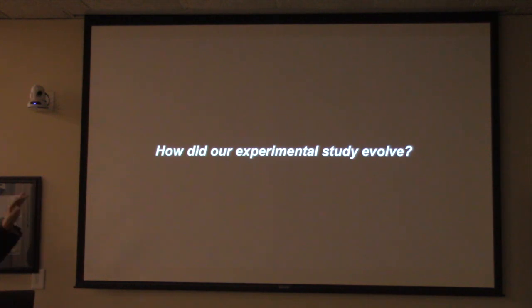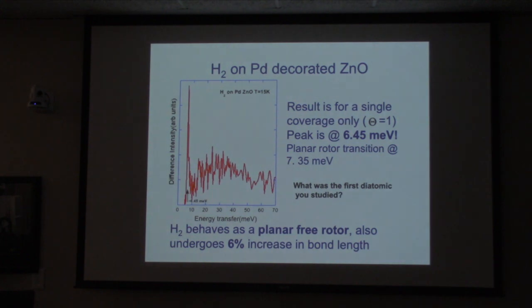So now I'm going to go back to that palladium zinc oxide problem. So here's what the ortho to para transition looks like there. It turns out that it's not near 14 millielectron volts. It turns out to be at 6.45 millielectron volts. And it turns out that when you have a single axis rotation, the ortho to para transition, both in graphite and the gas phase, etc., is symmetric. All right? But in this case, it looks like a merry-go-round. And that means the difference between the two transition levels isn't 2b, it's just b, the rotational constant.